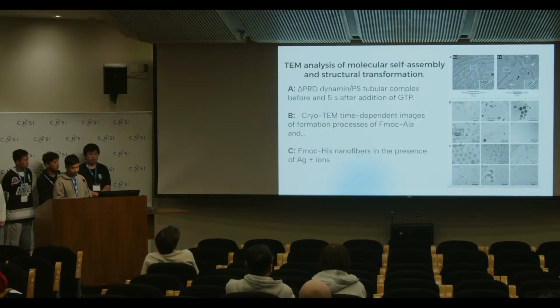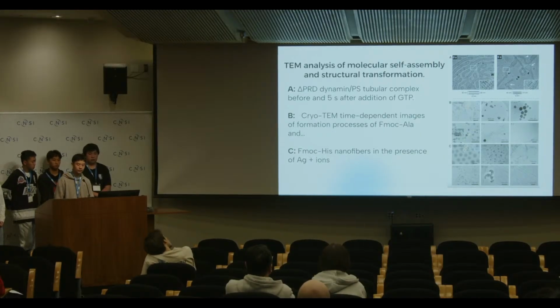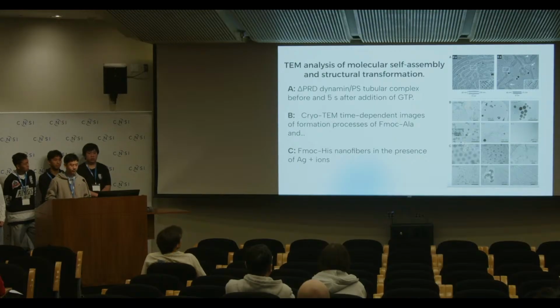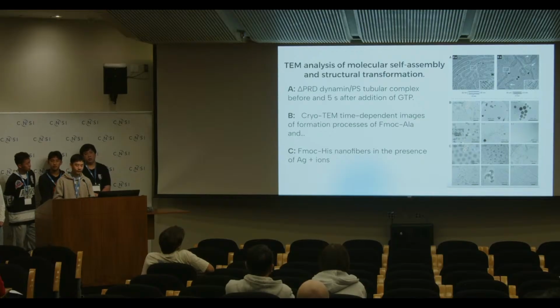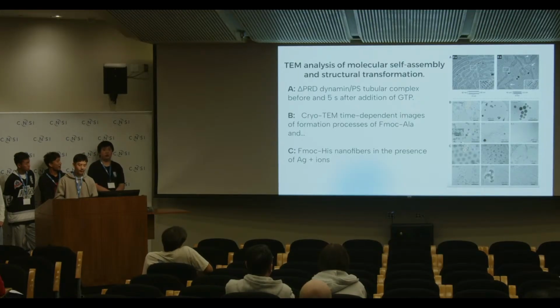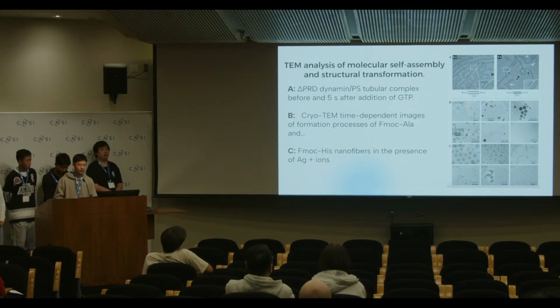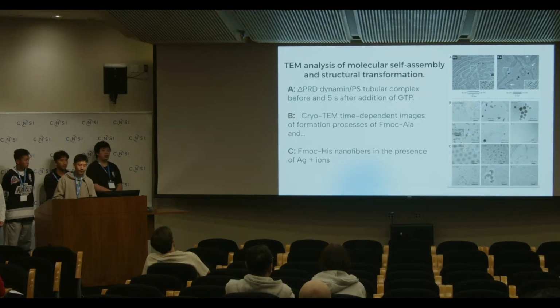In this first figure, you can see at 0 seconds, before the GTP addition, the complex forms uniform tubular structures about 50 nanometers in diameter, and after GTP, a progression of structural states appears. At 5 seconds, cryo-EM reveals a mixture of non-constricted and constricted tubes, and by 210 seconds, most tubes are constricted to 40 nanometers, and dynamin-free liposomes appear.